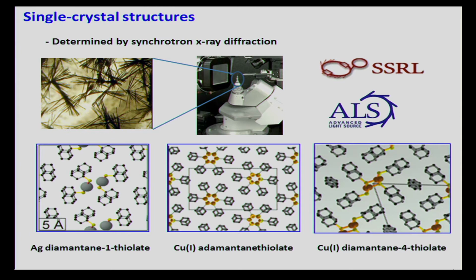What they have in common is that you have a long chain of alternating metal and sulfur atoms forming this backbone and elongating along the long axis of the crystal, and then you have the diamondoid species surrounding them. But the exact way they arrange themselves is quite different, and that's really modified by the diamondoid species. For example, shown here is a silver adamantane thiolate, that is a silver sulfide with an adamantane surrounding it. You can see that you have two pairs of silver-sulfur chains bonding together, and then you have the diamondoid sitting in what we call a cis position surrounding them.